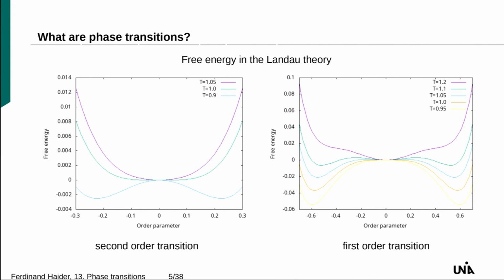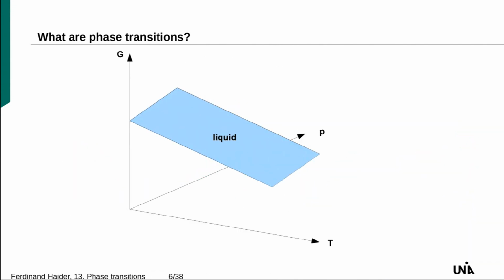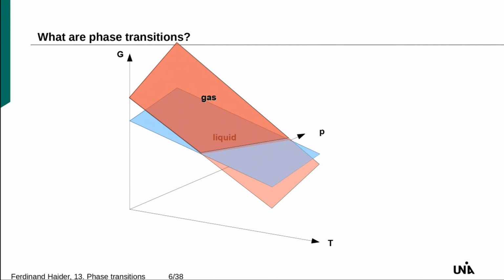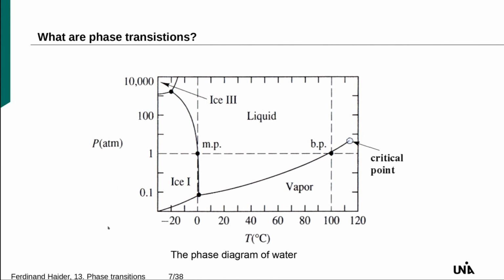And I think I skipped some part of what I prepared here. Perhaps just very briefly, what I did here until now was just G of T. But of course, you can also consider further thermodynamic parameters like the pressure. And I guess you know that pressure will shift phase transformation temperatures. So if you have a gas-liquid transformation, for example, this curve of free energy becomes a surface of free energy. So in the PT plane here, in the gas phase and the liquid phase, they have different, and they have not an intersection point, but an intersection line. And this you can project down to the PT plane. To the left you have liquid, to the right you have the gas phase. This is what is typically shown as phase diagram of liquids in the PT plane, of many materials.